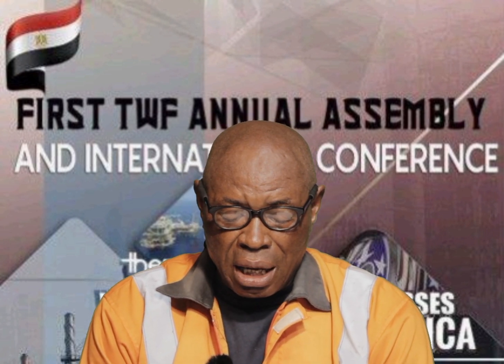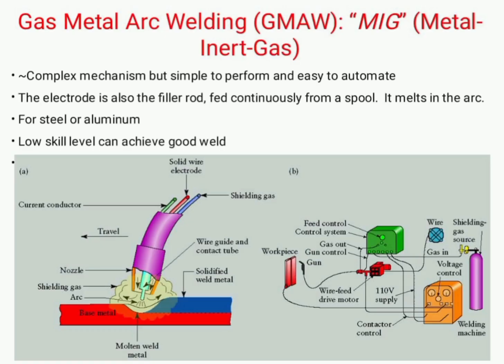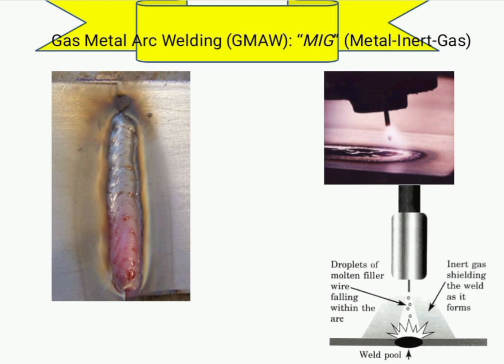We also have gas metal arc welding, which we call either MIG or MAG or GMAW. It's a complex mechanism, but simple to perform and easy to automate. The electrode is also the filler rod, fed continuously from a spool. It melts in the arc, for steel or aluminum. A low skill level can achieve a good weld, and it consists of the welding gun, the simple welding machine, the feed control system, the wire feed drive motor, and the shielding gas source. The welds done with GMAW are often very good welds and a little bit free of defects and flux.